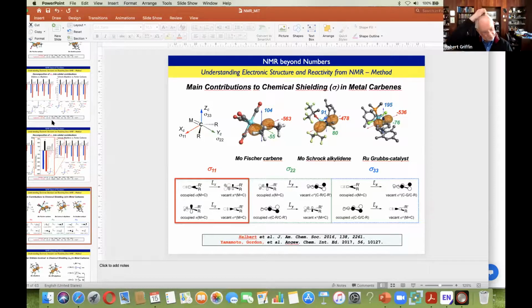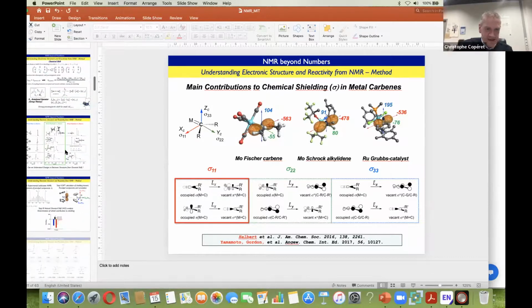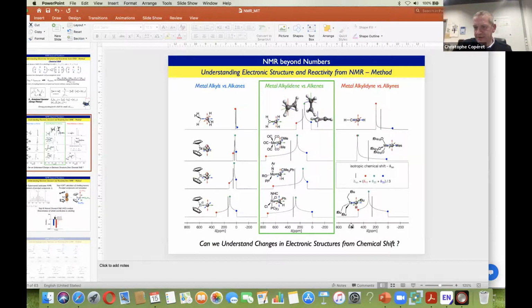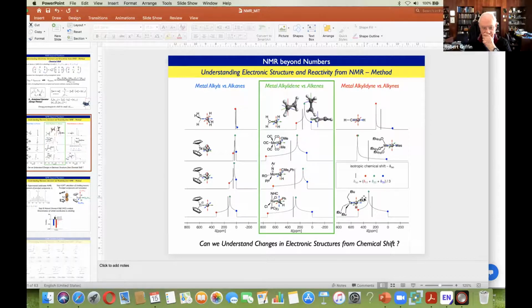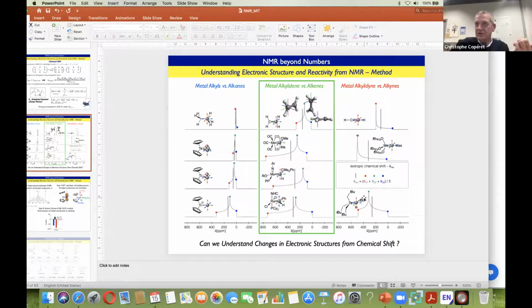Yeah. This happened, for example, in what I didn't discuss: if you take the infamous Schrock compound, the one that gave him his Nobel Prize, it turned out if you look at the tensor of this compound, it's actually closer to being sp than sp2. Because delta 2 has moved from below the isotropic chemical shift to above. So when you change hybridization from sp2 to sp, you see delta 2 contributing. But when you only see a contribution on the pi system, it's actually delta 1 which is moving. So it's really about, again, the symmetry of which orbital actually contributes to the chemical shift.